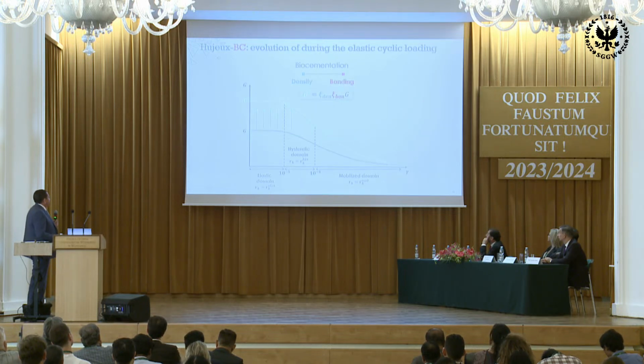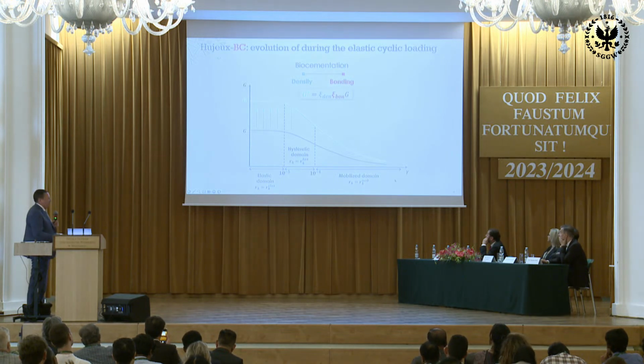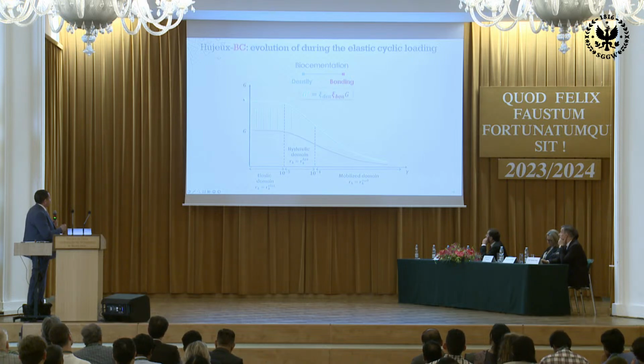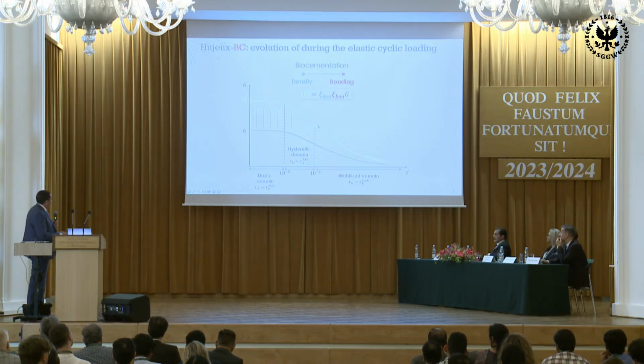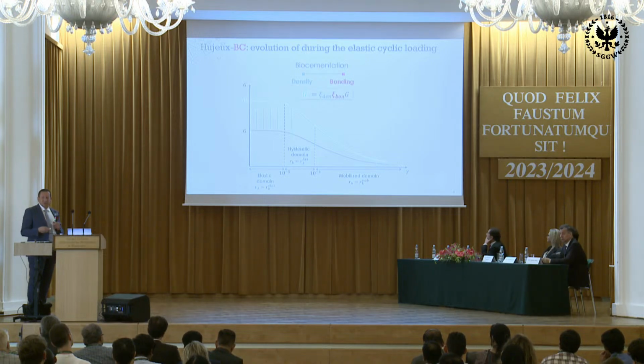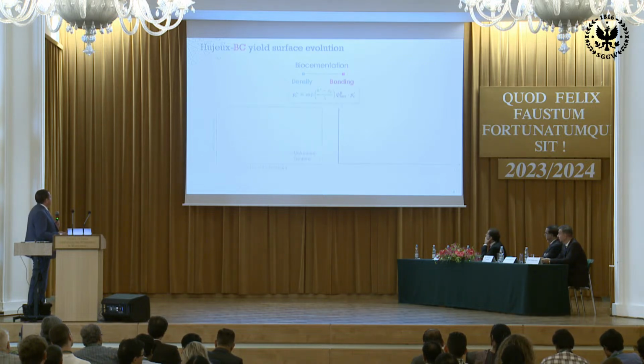The last rheological aspect is about the elastic domain. In the elastic domain, we have the G-gamma curves, for those who are familiar with soil dynamic analysis. Our G-gamma curve will change in that we are changing the shear modulus values by introducing bonding and density. And at the end, when we reach values of distortion of, let's say, 0.5%, then we recover the initial value. So the yield limit that we get at the end is this type.